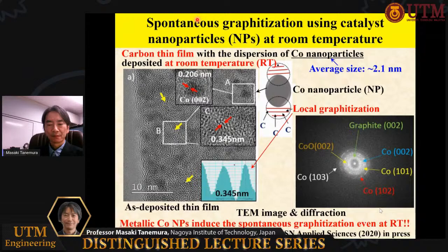We are also trying the low-temperature graphitization. This is not the carbon nanofiber, but the case of carbon thin film. And the cobalt nanoparticles are dispersed in the film. This is the as-deposited film at room temperature. The average size of the cobalt nanoparticles is about 2 nanometers.